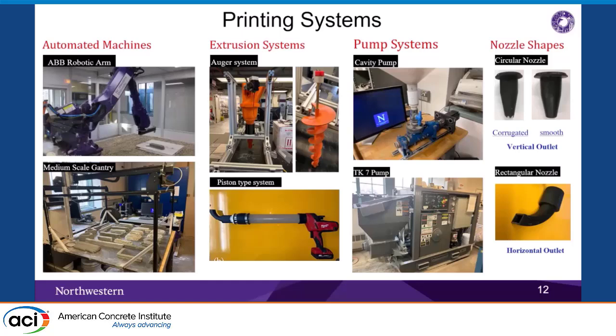It can pump the concrete really well. The good thing about it is that if you measure the rheological behavior of the mix before pumping and after pumping, it will be the same. And thanks to Dr. Cusatis for bringing this to our lab. Then for the nozzles, we have a circular nozzle, and also a rectangular nozzle.